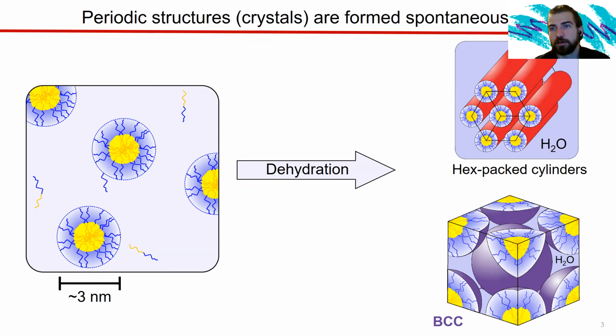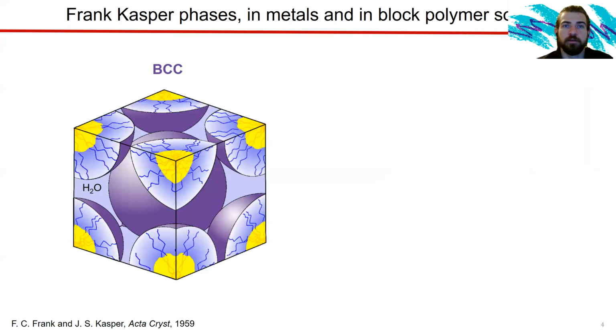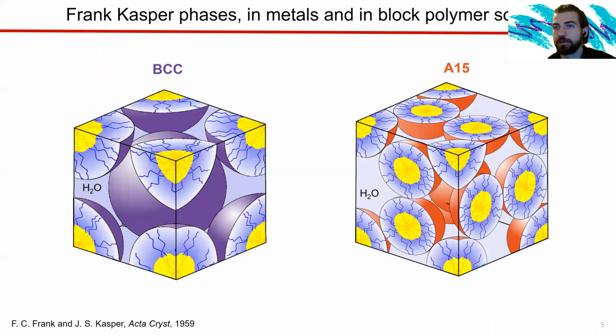So when we begin to concentrate these micelles, we can get the formation of structures such as hexagonally packed cylinders, body center cubic if they're spherical, or face center cubic. Now, in this system, we also have the formation of a Frank-Kasper A15 phase. Frank-Kasper phases were originally discovered in metallic systems in the 1950s. And in the last 10 or 20 years, people have begun to see them in a variety of soft materials, which is interesting. And sometimes they mimic similar findings that were originally found in metals.